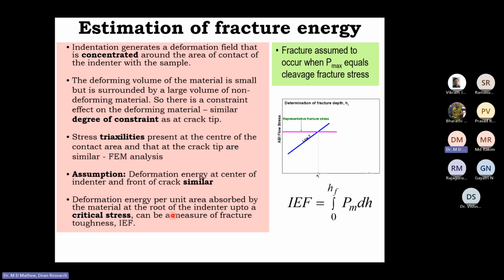So fracture is assumed to occur when the maximum load equals the cleavage fracture stress. That means I'm allowing the indenter to keep penetrating under increasing load to a point where the equivalent stress becomes the fracture stress. And then I calculate the energy that is absorbed by the material under the indenter. That energy is given by this equation, and that is the indentation energy to fracture.